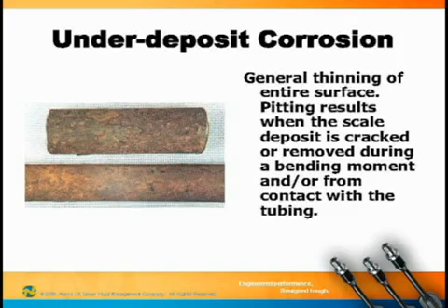Corrosion byproduct. One of the first things that's going to be done when it shows up in my office, I'm going to do a hydrochloric acid spot test, detection for iron carbonate. If you bead blast the sample because it stinks before you bring it to my office or most anybody else's office that's going to look at this sample, this is a useless test. You're going to bead blast the iron carbonate off. We won't have it available to test. Most likely you already know whether you have CO2 in your well or not, but it's still a test that's going to be run in most cases.